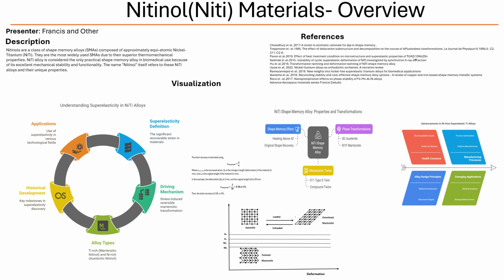For instance, in NiTiHf alloys, where you have hafnium added, the martensite can take on either a monoclinic or an orthorhombic structure, depending on the amount of hafnium. And each of these structures has different slip systems that are energetically favored. For example, in the monoclinic structure, a likely slip system is (001)[100], while the orthorhombic structure might favor (010)[100]. So the pathways for slip are kind of dictated by the specific arrangement of atoms in the martensite.